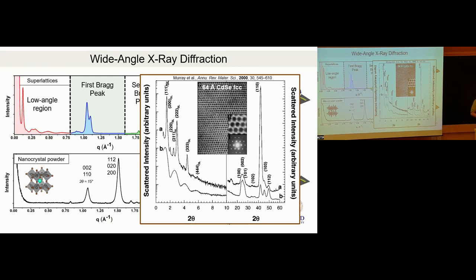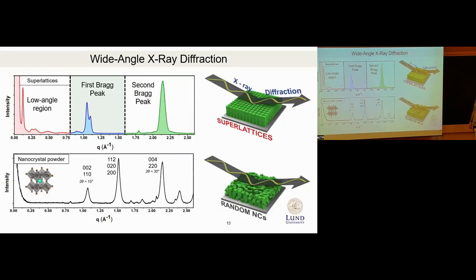So I have a question. I mean, why do you have these 1, 1, 2 peaks disappear? How is that possible? Because in the random sample, these nanocubes are oriented in all possible ways, so you see all crystal planes in the diffraction experiment. So you have to rotate the X-ray to see. Yes, yes. In this experiment, if we start rotating the superlattice with respect to the beam, then we start seeing other extinct reflections, yes. So you have a single crystal, basically. Yes, which also has preferred orientation with respect to the X-ray beam.